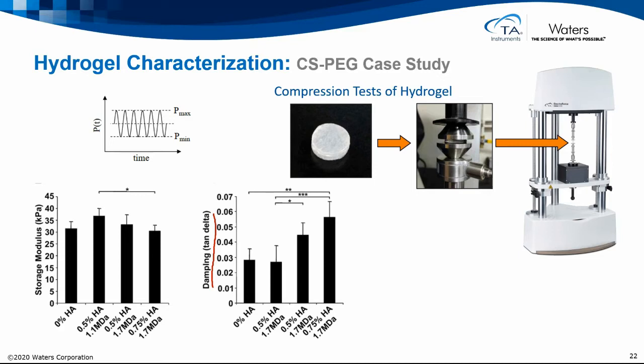What you see here on the x-axis is that as they change the ratios of constituents, you can significantly affect the damping. But if you look on the left, you don't change the modulus very much. So you now have a knob to turn that specifically drives damping. You have other knobs that we turned on the previous slide to get the modulus right, and now there's another knob to turn to get the damping right. I thought this was a very interesting multivariable study, with multiple ways to analyze the data to show these different parameters.